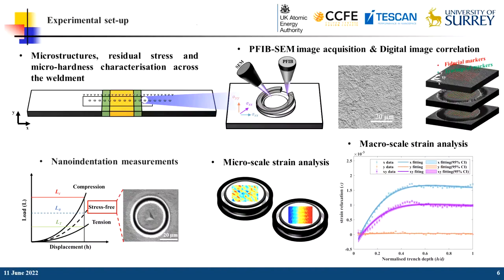So, how does the PFIB-DIC method work? The incremental milling step using the PFIB releases the residual stress gradually as the milling depth increases, and the image during the milling process is acquired in the PFIB and SEM dual beam system. The digital image correlation DIC technique is then applied to visualize the strain relaxation that enables the residual stress calculation. The master curve fitting evaluates the macro-scale residual stress, and our approach in this work can also provide two-dimensional, time-resolved, micro-scale stress relaxation maps.